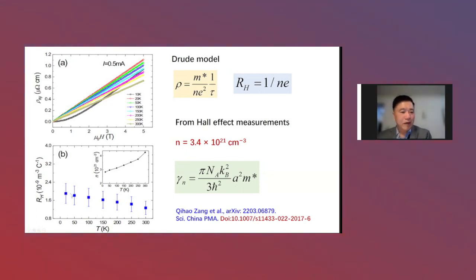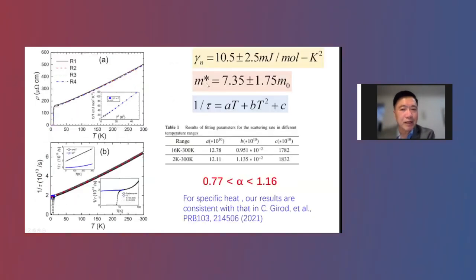We found that the Hall coefficient actually changes slightly with temperature. So we take the average to calculate the charge carrier density, which gives this value. And also from this specific heat coefficient, we determine this effective mass, okay? And finally, we get a mass of about 7.35 times the bare mass of the electron.